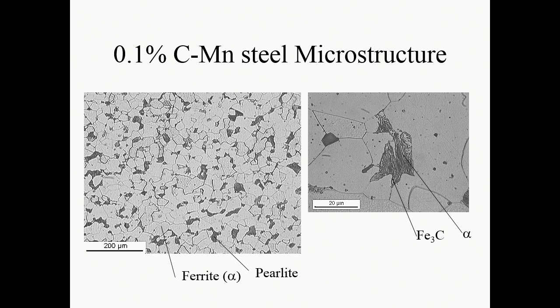So ferrite is iron, pearlite is iron carbide, is it? No. Because if you go to a higher magnification, if we look at one of those little perlite colonies, what you can see is that the perlite is made of these dark bands and light bands alternating, like alternating cards in a pack of cards. And the darker bands in this particular case are Fe3C, iron carbide, cementite, cement, sticking the two layers together, you know, that was why they called it. And also it's a hard material, it's a ceramic, and alpha iron. So perlite is not a phase, it's a mixture of two phases, but it was incorrectly described as a phase by the first metallurgists because their microscopes weren't good enough to see this.